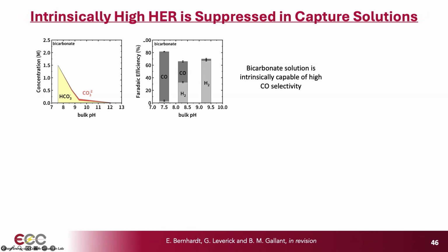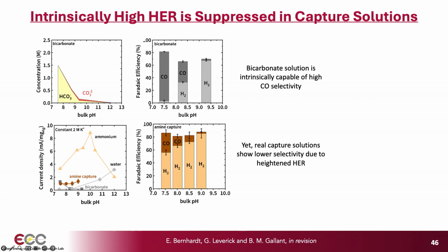So we also developed model bicarbonate solutions, as shown here. So this has just bicarbonate concentrations as a function of pH, mimicking the full capture solutions, but no amine. And you can see that we actually saw pretty good CO selectivities in this case. So this tells us that for the amount of bicarbonate that's present in the more complicated system, it's possible to get high selectivity. However, in the full capture systems, we're not realizing that just yet. We see lower selectivity, and that's because the ammonium are still getting to the surface and participating.